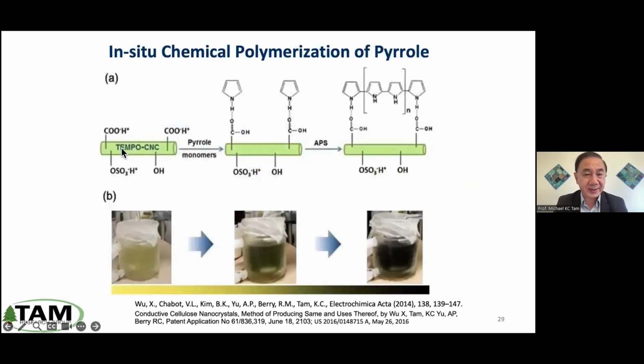She took this CNC, oxidized it, and put carboxylic acid groups on the surface. The reason was that you can then induce hydrogen bonding between the pyrrole monomer and the surface of CNC, and as you add the APS, ammonium persulfate, you can oxidize and polymerize this. From the bottom, you can see the solution becomes black, an indication that the reaction is proceeding. And then you polymerize the coating of the conductive polymer on the surface of the CNC.